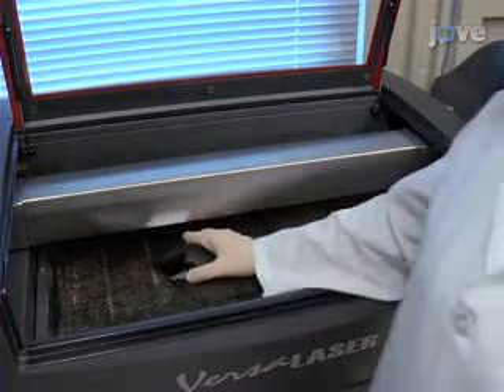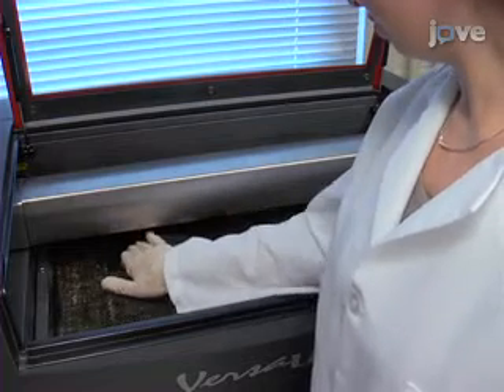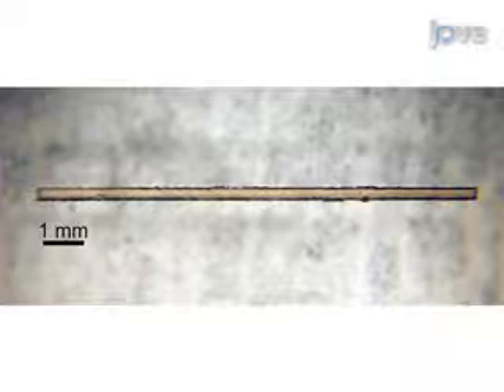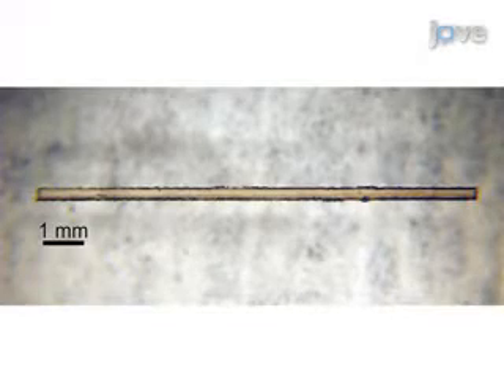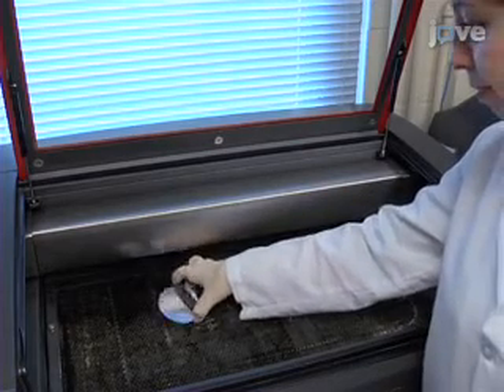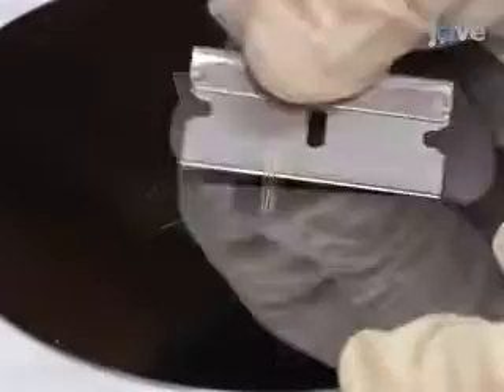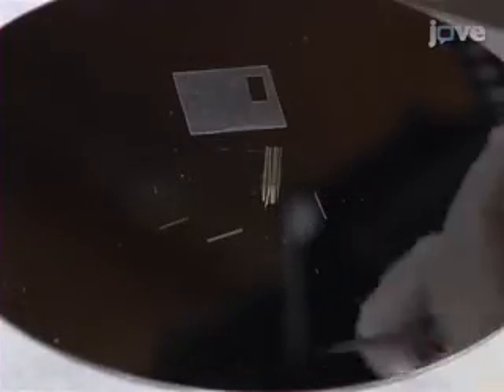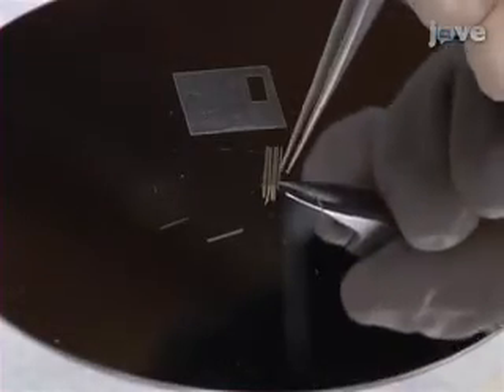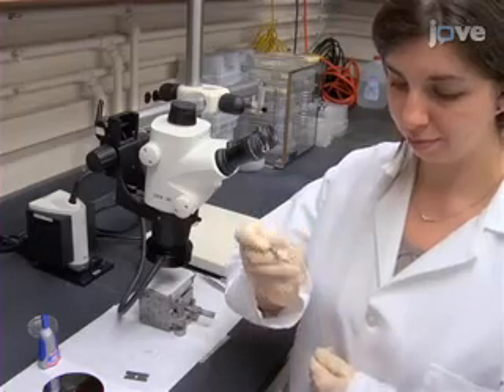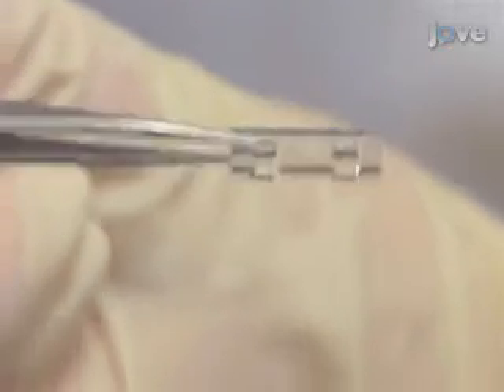Machine the samples for ex vivo experiments, referred to as implant samples, into beams 300 micrometers by 6 millimeters with a thickness matching that of the film. After removing the wafer from the micromachining setup, use a razor blade and tweezers to carefully release the samples from the wafer. To handle the samples, prepare acrylic holders designed to serve as part of the grip system in the